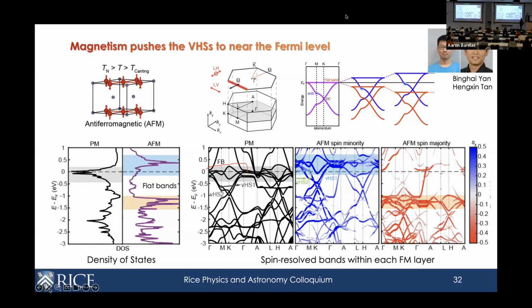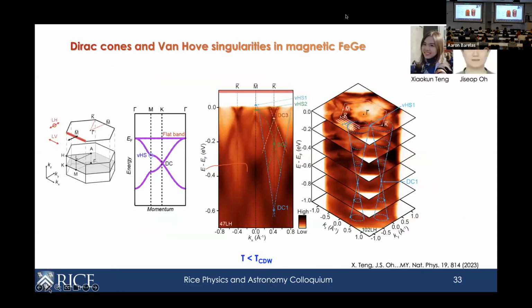So the end result is that because of the magnetic order, there are these Van Hove singularities that used to be far away from the Fermi level that get shifted towards the Fermi level, eventually landing there. And then that's where we can also have the presence of the charge density wave order. This is what we can also observe experimentally.